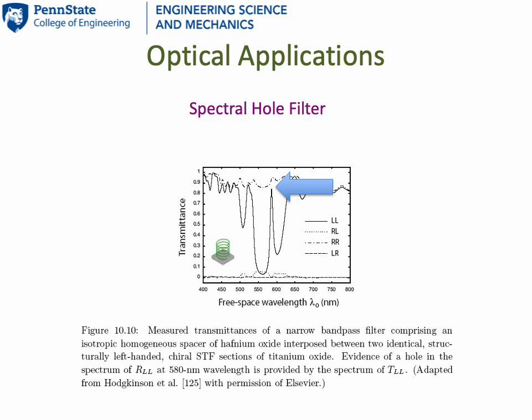The effect of the 90-degree twist defect is a transmittance spike in the spectrum. This transmission spike indicates a reflection hole. The circular Bragg regime is generally 50 to 100 nanometers wide. The spectral hole is about 10 nanometers wide.